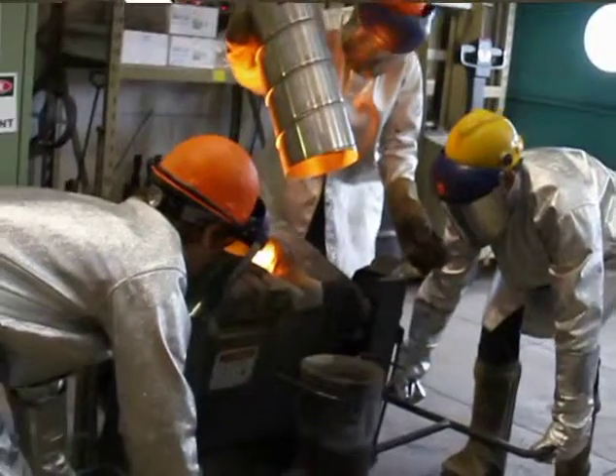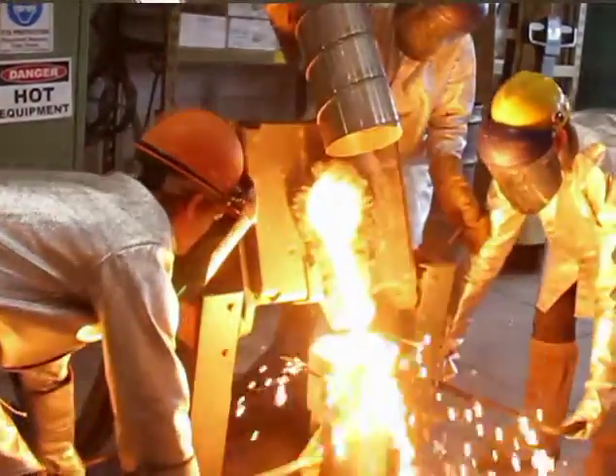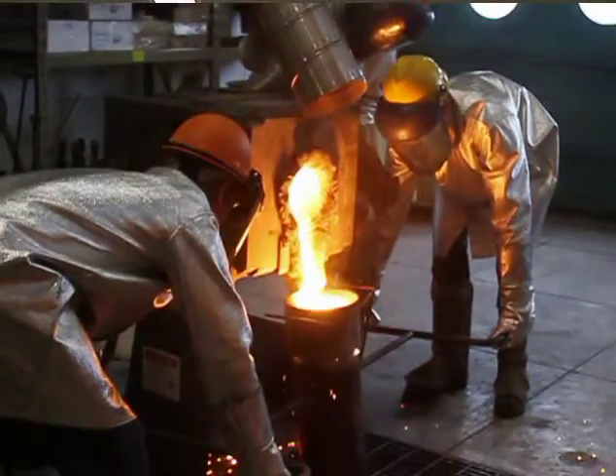In order to do that, we had to look mainly at some of the spheroidizing elements. Magnesium is one of the main spheroidizing elements, but it has a rather quick fade time, which means it gets released from the part very fast. So we looked into other elements — rare earth elements — which also cause these nodules to spherize.